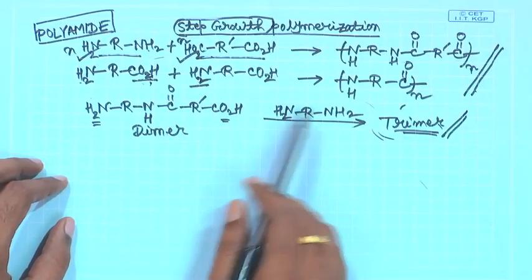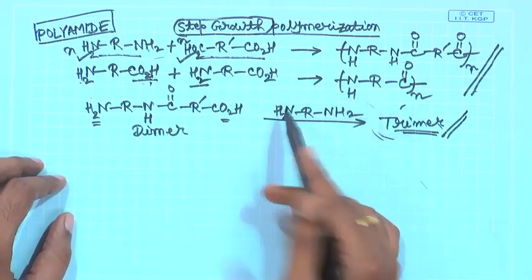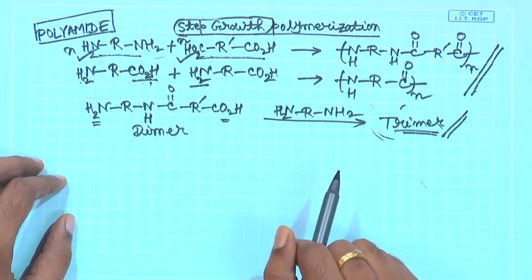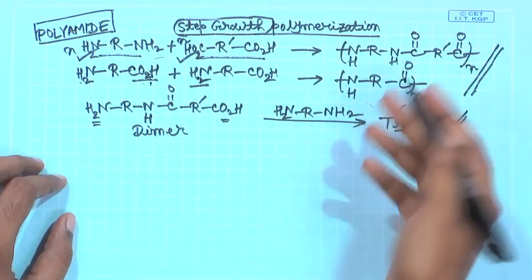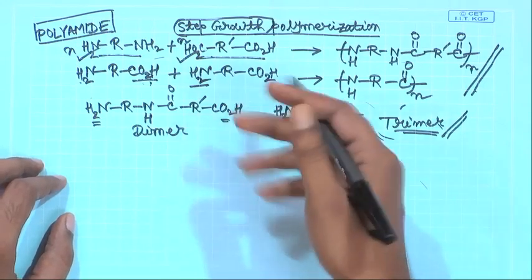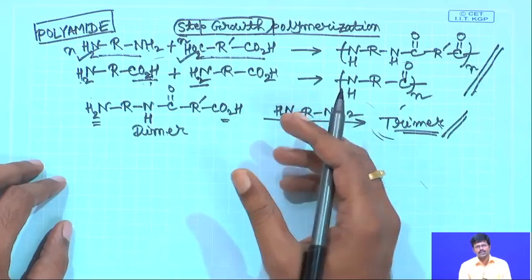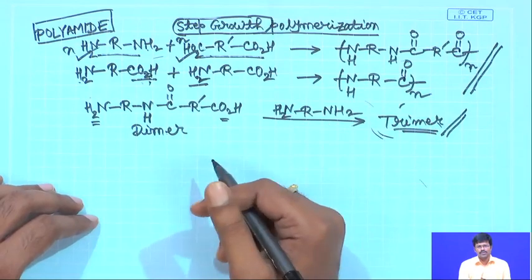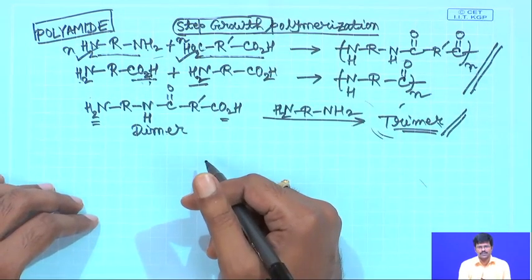So if you are looking towards that kind of situation, what you have to do is that you have to analyze the kinetics of these reactions, because if you can analyze the kinetics, then only you understand the principle fully, the mechanistic aspects of that fully, and then you know how you can control the molecular weight. And you will see that at least 99% of conversion is necessary from the monomers in the step polymerization, so as to have polymers of any practical significance. That means the molecular weight will be much low if you are say even at 95% conversion.